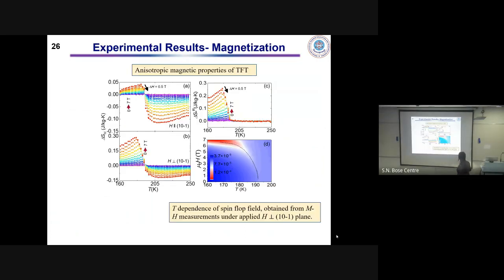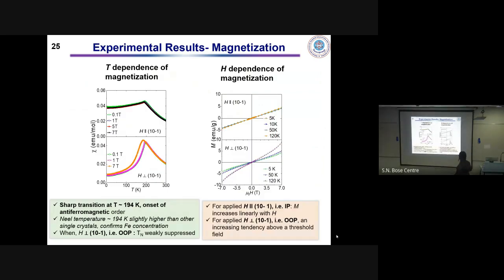Is it reproducible? Have you checked? Yes, it is reproducible. We have done measurements on a number of crystals of the same batch as well as different batches. And why I am saying it is spin flop is also because, as I show, as I'm increasing the temperature, the spin flop field is getting reduced. So this also gives an indication that spin flop is happening in the system.